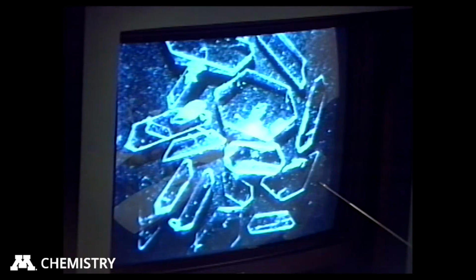And these crystals, upon heating or sitting on the bench top, will start to transform. Those of you who were here this morning have already picked this out, haven't you? That there's a crystal reaction taking place. It's actually a polymorphic transformation, and I'll show you this in more detail in a minute. So 2 is going back to polymorphic form 1. These are metastable crystals, and they're going back to the more stable form in the solid state.